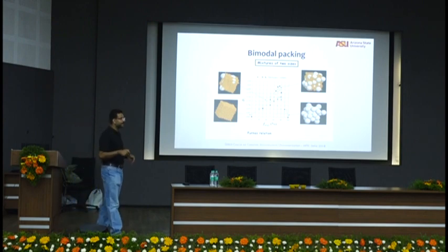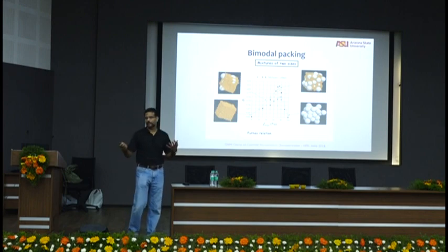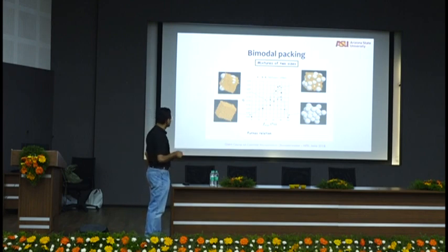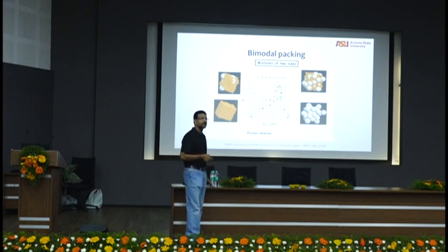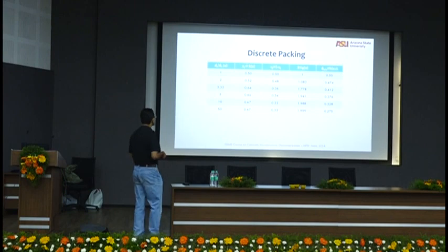So the idea is that when I say large, it means the largest possible particle that you can use. Maybe your large coarse aggregate is a certain size, below which you then need a bunch of smaller particles forming that proportion so that you get the optimal packing density. So that is what you're looking at in mix design most of the time, to get an optimal packing density.